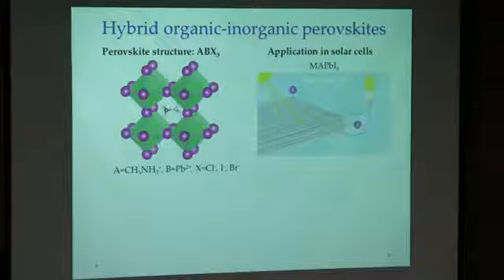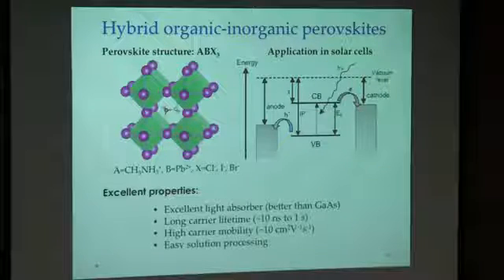So if we look at the photo conversion process in the solar cell, we know that a photon shines on the material and creates electron-hole pair. Electrons get collected by the cathode, and the holes are collected by the anode. That gives electricity. So in this process, we know that it's only possible because of the excellent optoelectronic property of the perovskite here. For example, it's an excellent light absorber. And the long carrier lifetime and the high carrier mobility facilitate electron-hole pair dissociation rather than recombination. And it's amazing that all these excellent properties are realized on materials that's processed with solution. That means you just mix solution and a spin coat, nothing high technology. You get these nice properties.